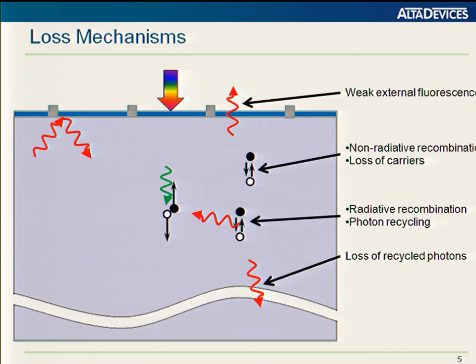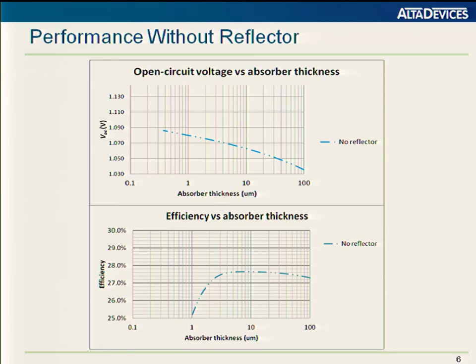So you have all of these band edge photons rattling around inside this device. Some of them will be reflected. Another point I want to make is the angle is randomized by this process. So we have mostly normal photons coming in from the sun, and then this random distribution of band edge photons. So half of them are basically going deep into the optical structure, this thick semiconductor. The other half are hitting the top surface. A small fraction are within the escape cone of the top interface and are able to escape from the device. So even on an on-wafer device, you are going to see some emission. And you can use these as a kind of LED if you do electroluminescence on the cell.